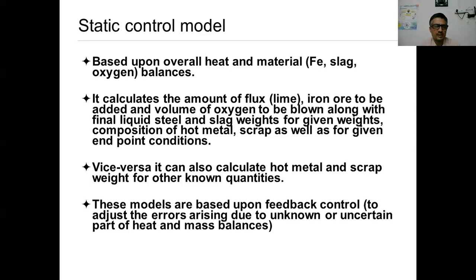That means that since it is a batch process, even if you do the heat and mass balance in whatever possible manner, or even if all compositions and weights are available, there may still be some error. The error may arise from the measurements, or from the non-availability of compositions, or maybe the composition you are using in the current heat corresponds to some previous heat, and the current compositions are not available. All these calculations, no matter how accurately you do them, will always have some error. So in order to adjust those errors, these models use feedback calculation, to adjust those errors arising due to the unknown or uncertain parts of the heat and mass balances.